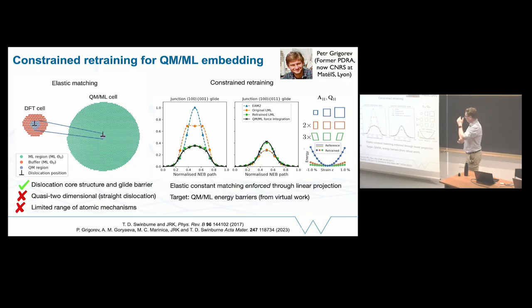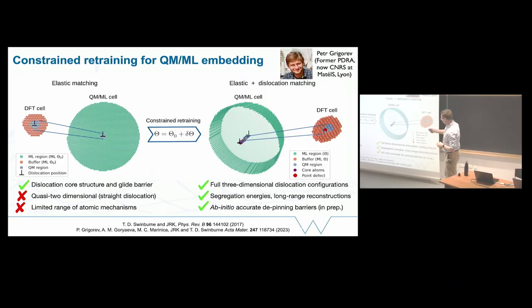This is work done by Petr Grigorev, who some of you may know has just started a permanent CNRS position in Lyon. He was a postdoc with me and then with Tom Swinburne in Marseille, and is now just starting his own activities. So what Petr did was to use these ideas that I showed you on calculating energy differences by integrating forces. We do that in this QMMM style setup, and we know then what the reference results should be, so what the energy barrier, it's called the Peierls barrier. You apply a stress and dislocations move, but it's just an energy barrier which you compute with NEB. We know what it should be, and we have our original potential which doesn't get it quite right. We update the potential a little bit, so as well as describing the bulk material, it can describe this particular process. And the motivation for doing this is that then we can do this 3D business.